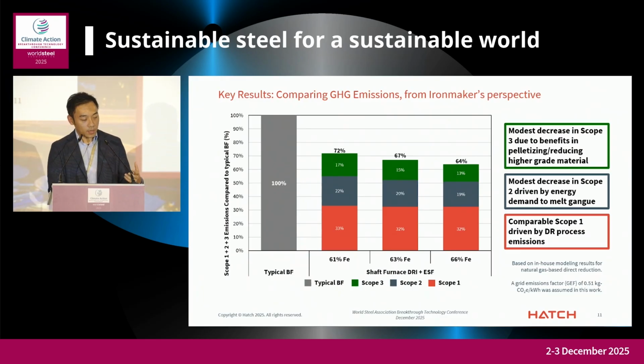So the second thing is we look at, so we know the ESF is very effective at removing gangue, but the question is still, for a pyrometallurgical electrified process, is it really energy efficient? And of course, from the energy and emission perspective, is it the best and most efficient way of rejecting that gangue versus beneficiation? So what we did is unbeneficiated, moderately beneficiated, and heavily beneficiated Pilbara iron ore in the ESF process. What is its impact on emission compared to, let's say, I won't say typical, but a very well-performing BF producing pig iron? And we broke down the emission by different scopes, from the iron maker's perspective, of course.